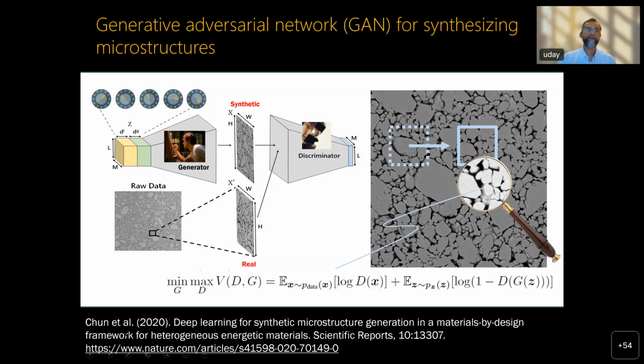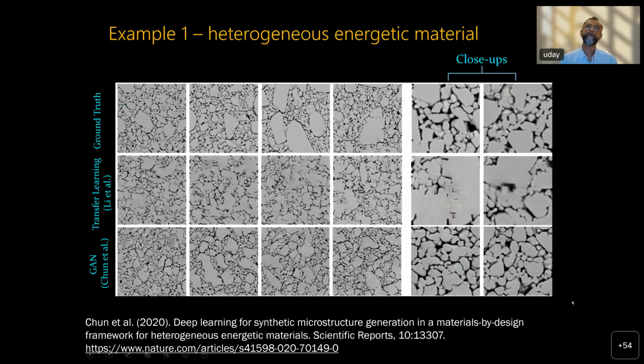So that's the strategy, and it's in the paper by Chun et al. in 2020. And basically, what we have shown in that paper is that we can take one snapshot of an energetic material microstructure and generate many similar microstructures with similar characteristics. So then we can do numerical experiments on them. So these are some ground truth samples of microstructures that we obtained from AFRL. The middle row is a transfer learning based approach and results from that, and the lower row is the final GAN approach that we settled on.